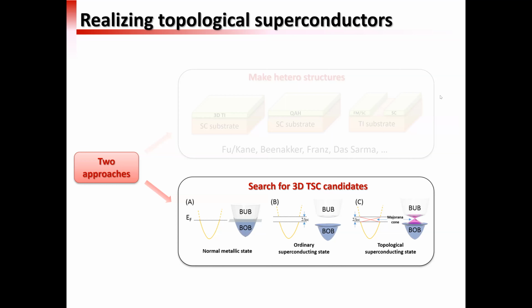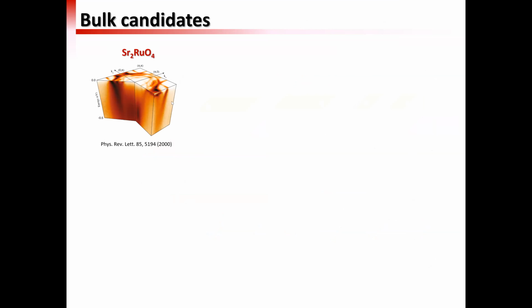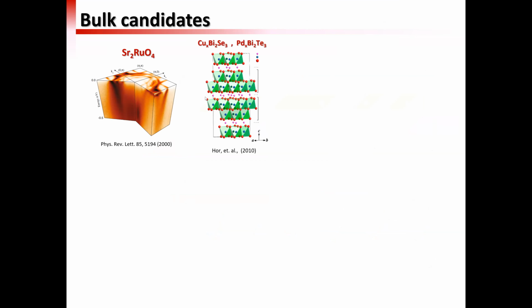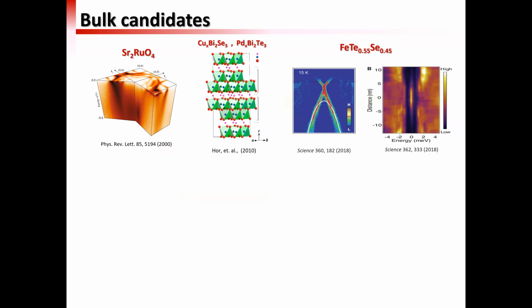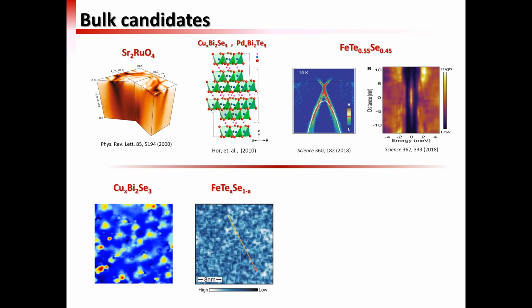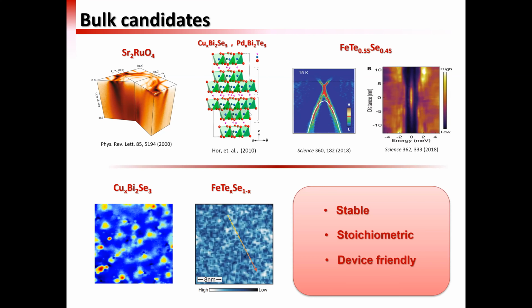There are already a few unconventional or topological superconductor candidates among bulk materials, for example, strontium ruthenate. Of course, there are also some new discoveries about the measurement of this material, and we'll wait and see what the real physics in there is. There are also others, such as copper-doped bismuth selenide, palladium-doped bismuth telluride, and more recently the iron tellurium selenium system, which people realize could be topological superconductor candidates. But many of these materials have some shortcomings. For example, a lot of them are doped, so they are not stoichiometric, and sometimes they are unstable, like copper-doped bismuth selenide, so they may not be very device friendly.